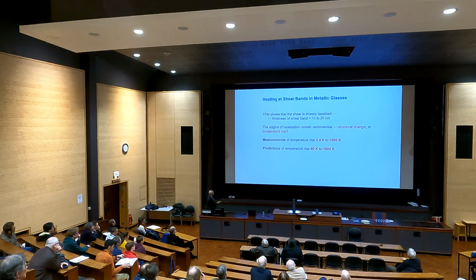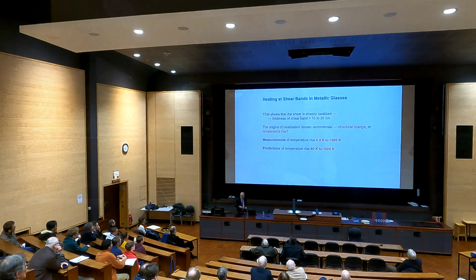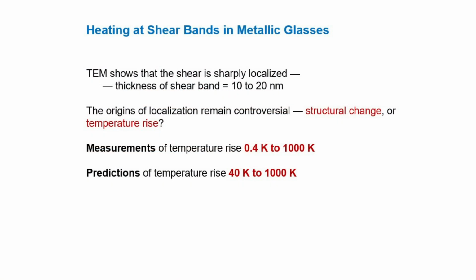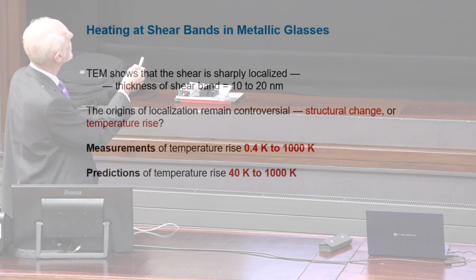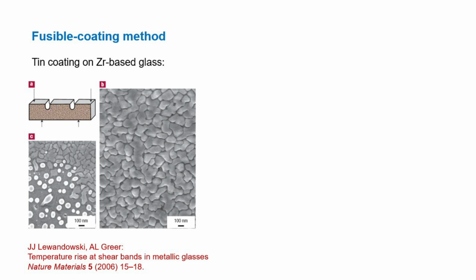Well, existing measurements and predictions were haywire, and no good guidance at all, so we thought we could try and do something about this. And it was to say, well, how are we going to detect this local heating, if there is any? We will take the metallic glass bar that we want to break. This is macroscopic, it's several centimeters. Notches, you deform it, but on this surface we have applied a coating of tin, which would look like this. Tin, of course, is a low melting point. That's the key part of the story. And we verified with a laser flash that when the tin does melt, you can detect that it is melted because you get these droplets.